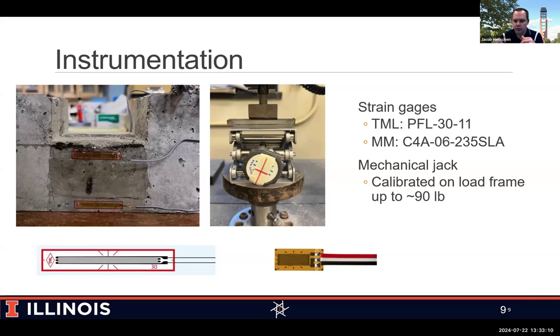And so what we did is we took it to a load frame with a calibrated load cell, and then basically set the height to that opening within our concrete beam. And so then we built our own custom calibration curve with the position of our turning screw and the corresponding applied load. And so we were able to get several measurement points that we had good confidence between applying 0 load all the way up to about 90 pounds.